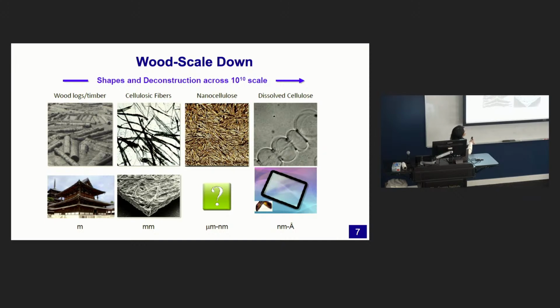When you disintegrate this cell wall structure, you get cellulose fibers that are millimeter size, and they have a high aspect ratio. So maybe the diameter is about nano size. And if you remove the amorphous phase of the cellulose, you get nanocellulose, and this one has a high aspect ratio, but you get the diameter definitely in nanometer size, or maybe the length also nanometer size. And then you further degrade to the nanometer scale, so you can get dissolved cellulose. So you can make liquid crystal from cellulose. So this is one example. We scale down the size.